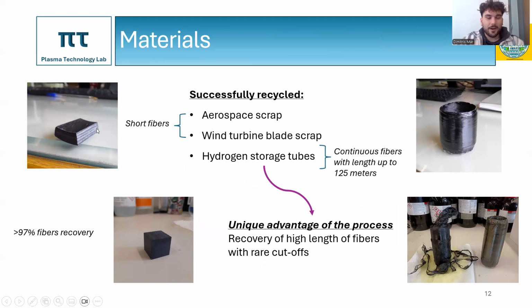With this specific setup, we have recycled large amounts of composites. We have recycled some aerospace scrap right here, and some wind turbine blade scrap right here. And from those two types of composites, we have recovered short fibers. But the unique advantage of this process is that we can recover long fibers with rare cutoffs. For example, we have recycled some hydrogen storage tubes, which you can see right here, where we can recover continuous fibers with lengths up to 125 meters. In every case, over 97% fiber recovery is achievable.